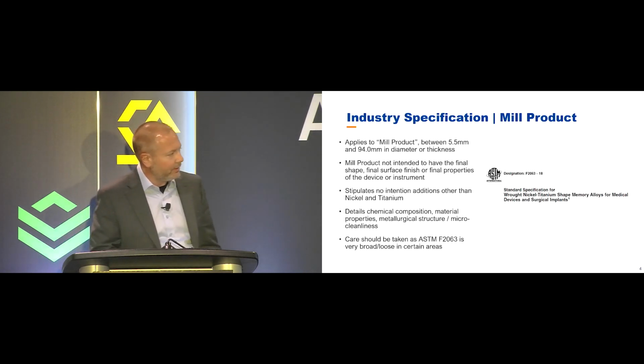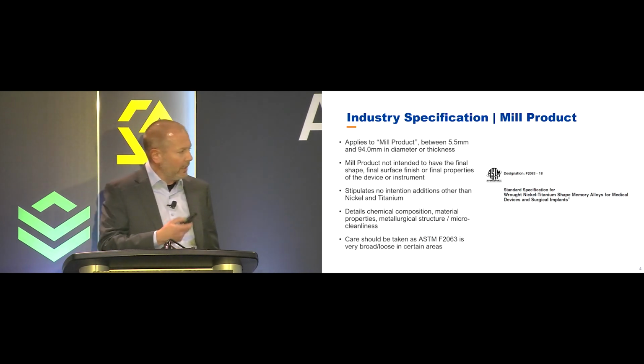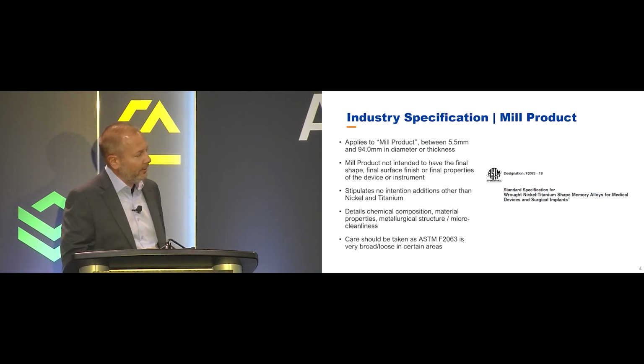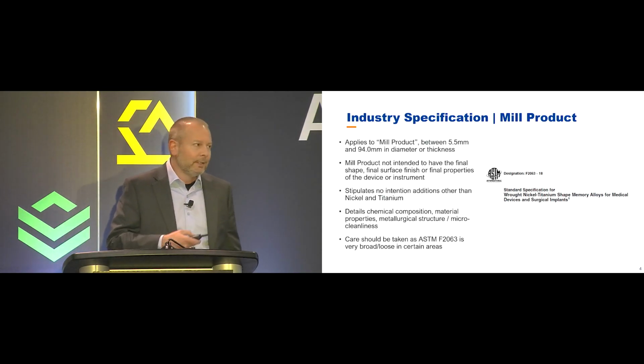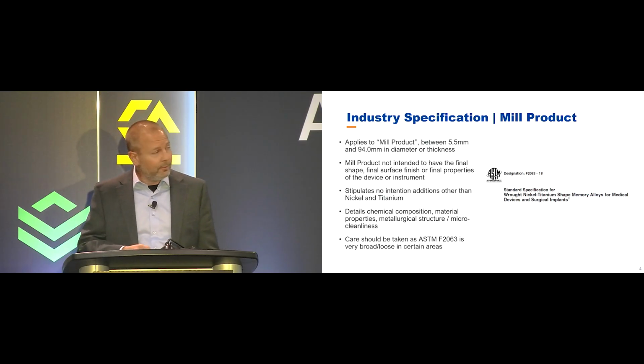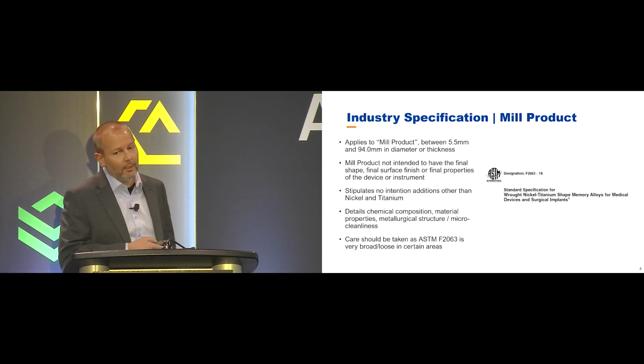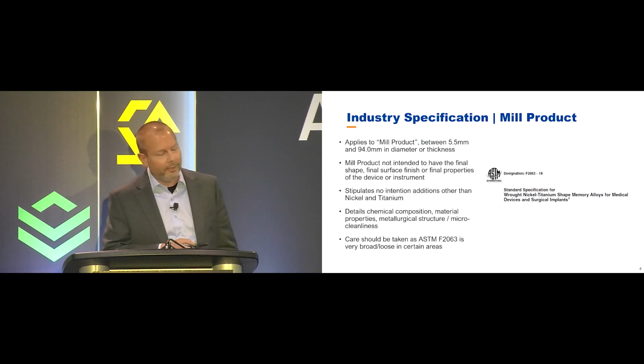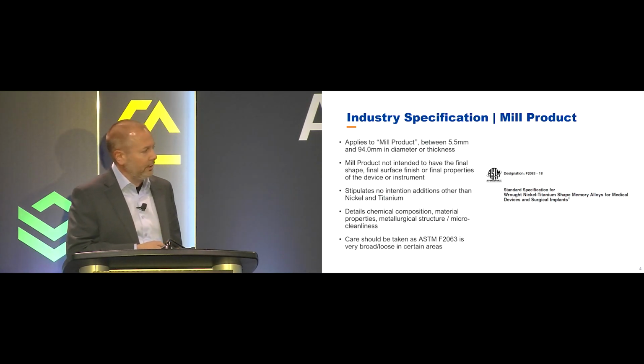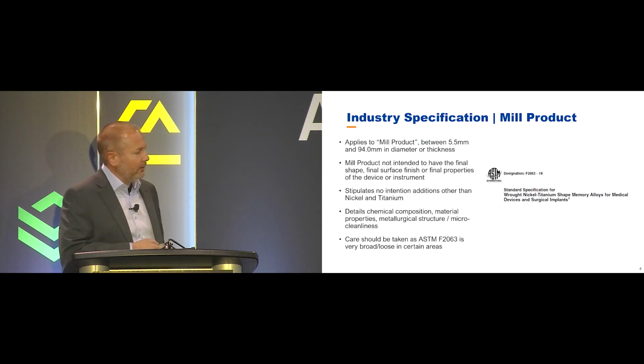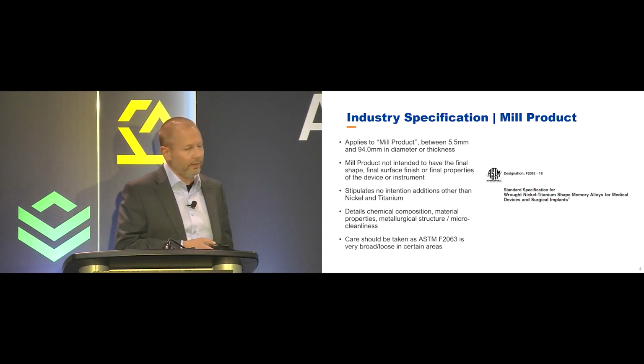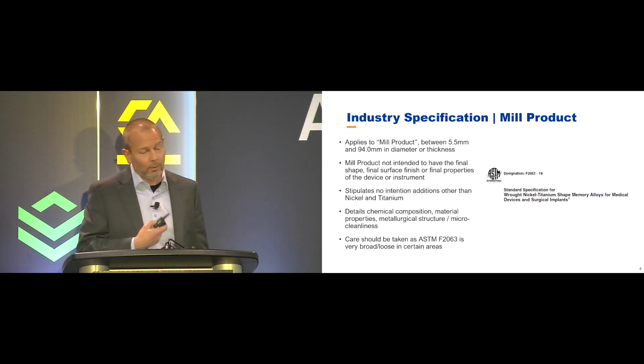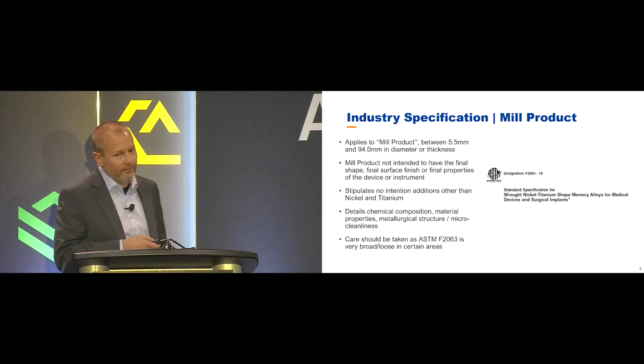So this is the spec that we melt to. This is not a technical presentation. I won't go into this line by line, but I just want to point out a couple things. When you see on a drawing per ASTM F2063, if it's a final component, the spec doesn't apply to the component. If it's a tube, it doesn't apply to the tube. It only applies to very large product, between 5.5 millimeter and 94 millimeter, hot rolled condition, and that's where they're speccing out the inclusion profile, the grain size, mechanical properties, chemical composition, things like that. So that's all done at this larger, what we'll call a mill product level. And that's kind of the scope of this talk here.